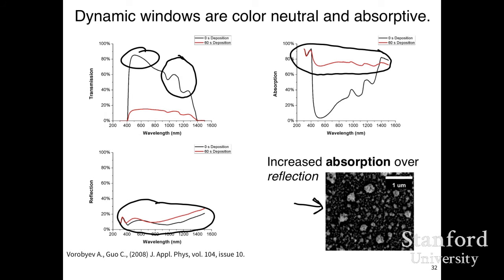And there are even laws in Singapore, for example, saying that the windows cannot reflect more than 30%. Because then you can just send light over to other buildings. And also, if there's a little bit of curvature in the window, you can have a light focusing effect, and certain spots can get very hot. So for a lot of the applications, it's probably very good that these films are absorptive and black.